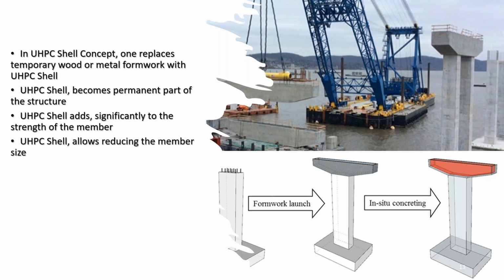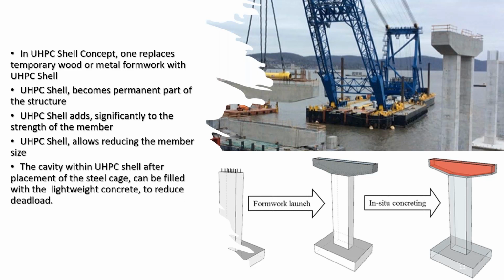As a result, it allows you to reduce the member size. And then the cavity within the UHPC shell can be filled with even a lightweight concrete, which results in reducing the dead load. And because nothing really penetrates through the UHPC shell, since the rapid chloride permeability number for UHPC is extremely low, it becomes almost maintenance free.